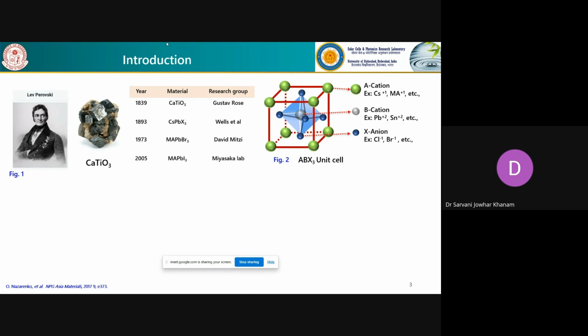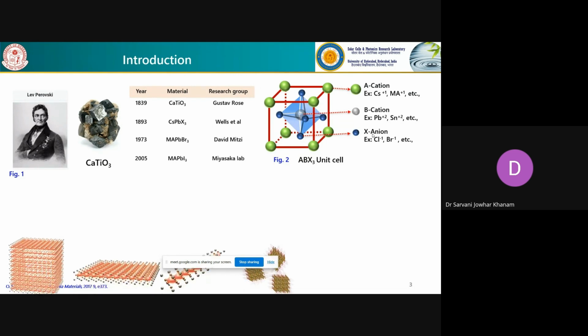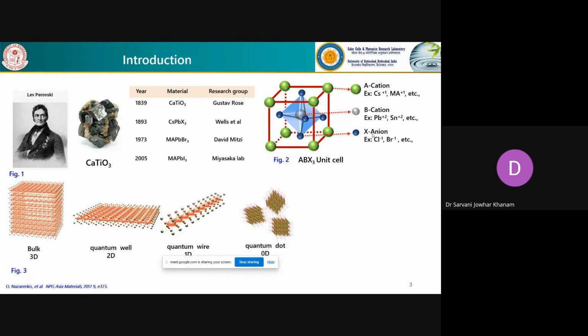Here we can see the B cations coordinating with the halide anions, forming an octahedra. Depending on the arrangement of this octahedra, we can differentiate this material into 3-dimensional, 2-dimensional, 1-dimensional, and 0-dimensional. The beauty of this material is that we can tune the dimensionality, and we can confine the dimension of these materials accordingly, depending on the application.